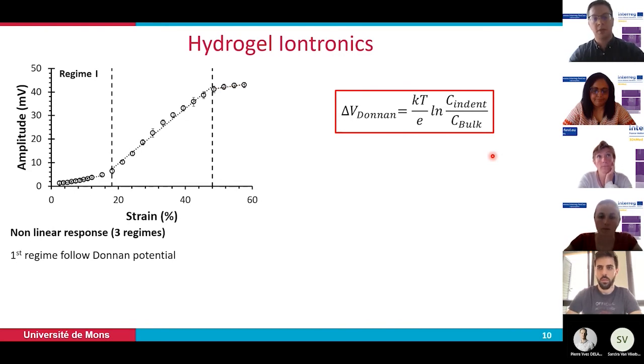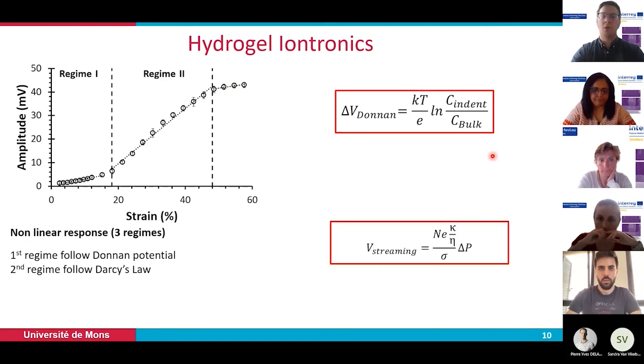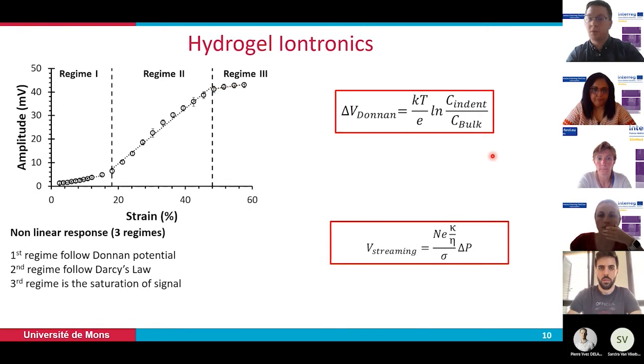But when you increase your strain, as you are with a swollen material, what happens is that you have a streaming behavior. So the amplitude starts to follow Darcy's law, which is completely dependent on the pressure that you apply on your material. And then at really high strain, you have a saturation of the signal, which is completely normal.